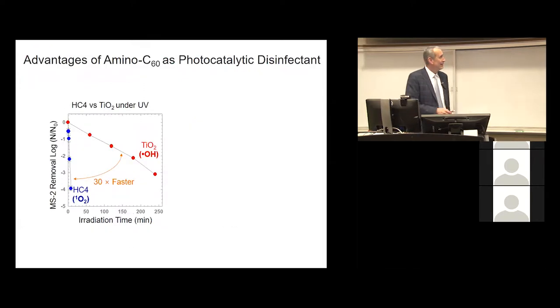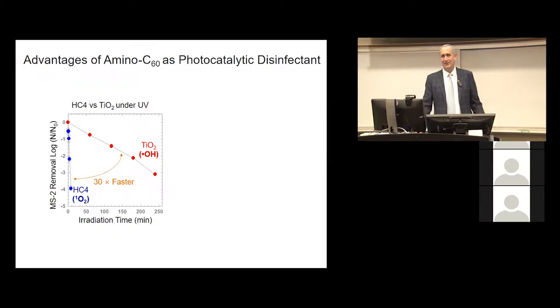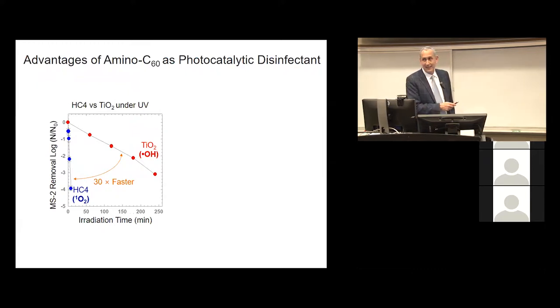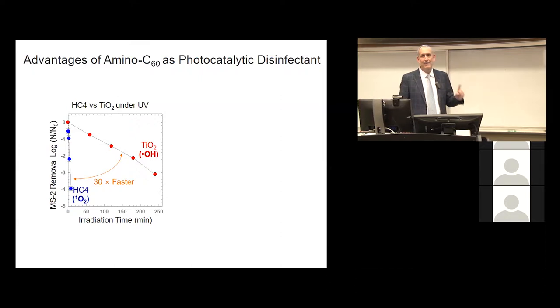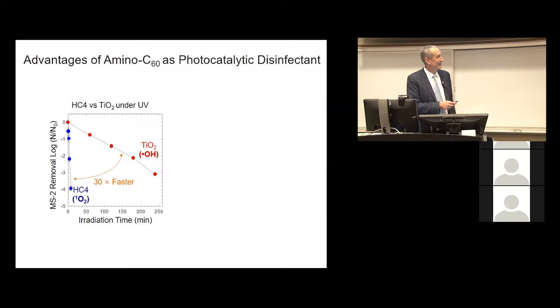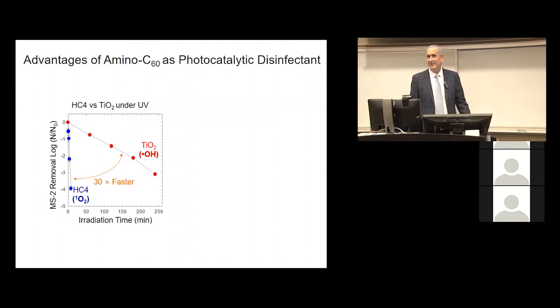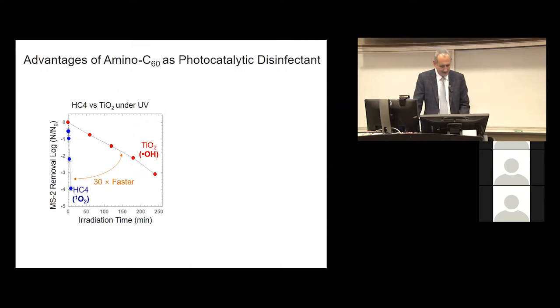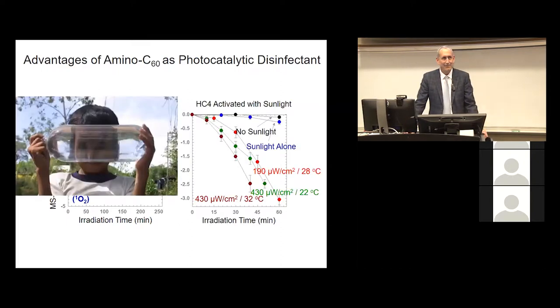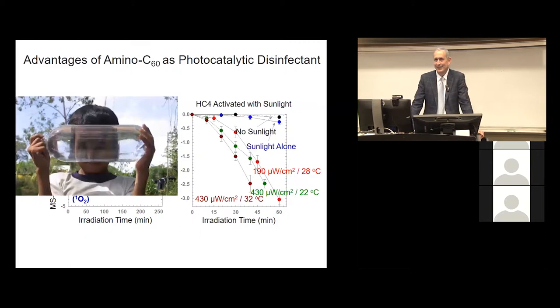And here we're comparing the performance of that amino fullerene to titanium dioxide, which is P25, the gold standard of photocatalysts. This is making a much stronger oxidant. But here, as you can see in this example, selectivity trumps power. This more selective photocatalyst that attracts the target is more effective in disinfecting. And of course, it has the advantage that it can be used with sunlight in places where you have no electricity, which is usually where you need disinfection the most.